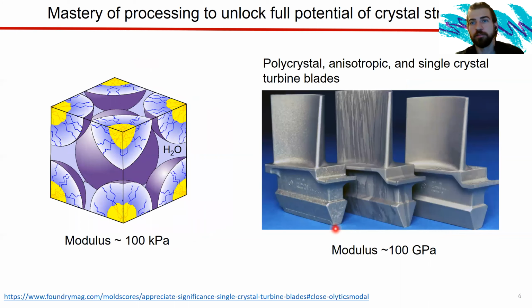Okay, so the reason that processing these systems is important is because by processing them, we can achieve the properties you want. And an example I like to talk about is metallic turbine blades. Now, you can see here several steps in the path to a single crystal blade. At first, they made polycrystalline blades, as you can see here, and it was found that grain boundaries actually expand more than the crystal itself. And when you have expansion, you lose efficiency. So the next step was to make very long stretched grains. And you can see each one of these is actually a crystal grain, where you have a continuous crystalline lattice without a boundary or defect or rotation.